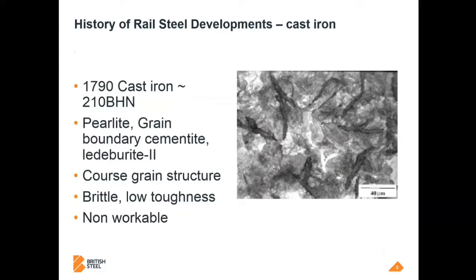So cast iron then. Cast iron at the time was relatively crude: coarse pearlite colonies, grain boundary cementite, and ledeburite, transformed ledeburite microstructure, a very, very coarse structure, very brittle and very low toughness, but reasonably strong. You get a reasonable hardness out of it, 210 Brinell hardness, but poor toughness,